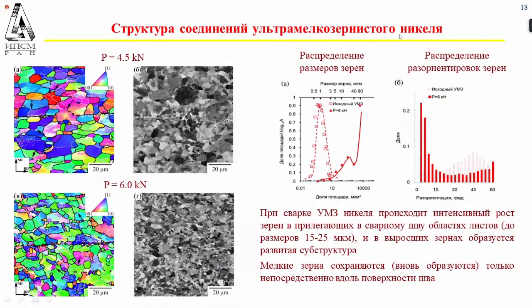And we found out that in the grains which were close to the seam, the number of them has grown. And there's only one thin layer of ultrafine state. But mainly what happened is the intensive growth of grains. And in recrystallized grains, there is a developed structure.